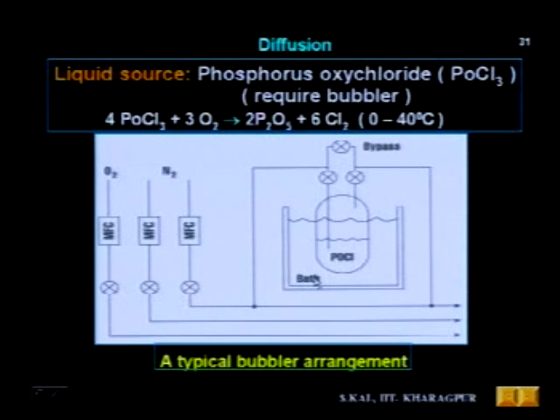If I maintain the bath temperature at a particular temperature, and if you dip this module, that means the container of POCl3, into this bath, then it will attain the temperature of the bath. And now these are different valves, and if, for example, this bypass valve is closed, and you open this valve and this valve, then the nitrogen gas will flow through this path into the bubbler, and it will bubble through the liquid, and when it flows, it will carry some of the POCl3 vapor along with it, and this POCl3 and nitrogen will flow into the tube through this path.